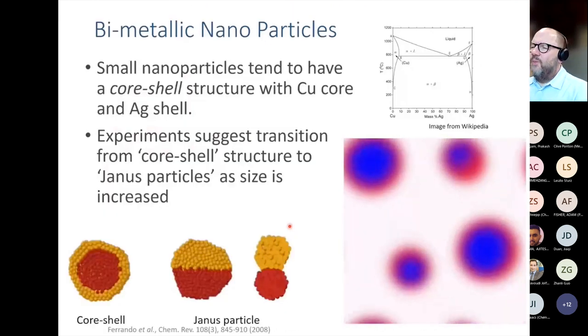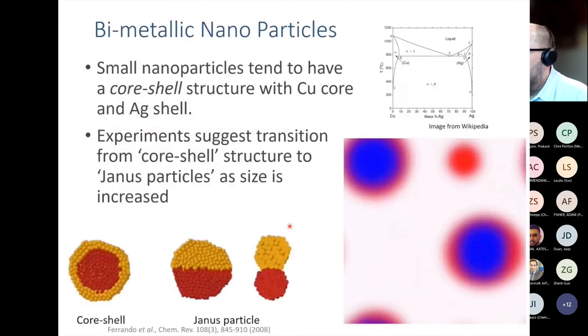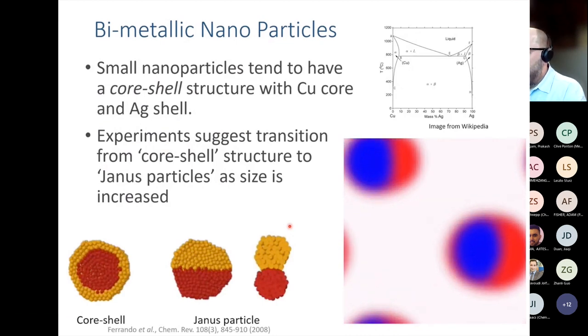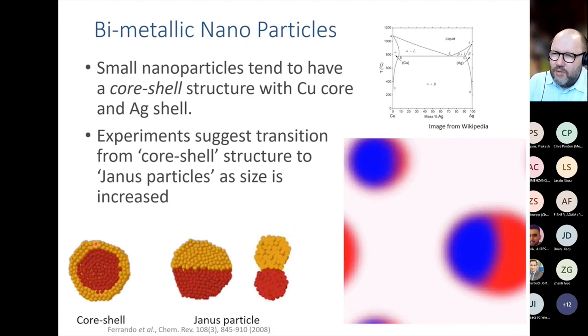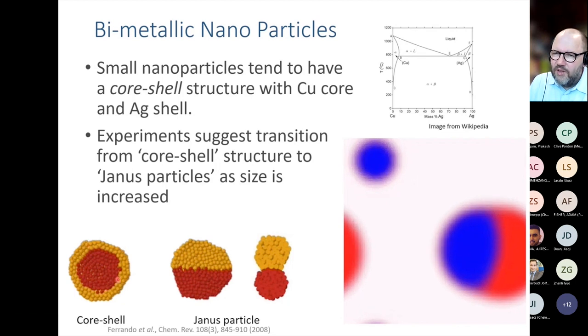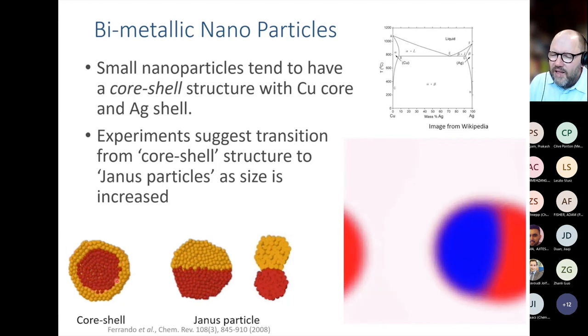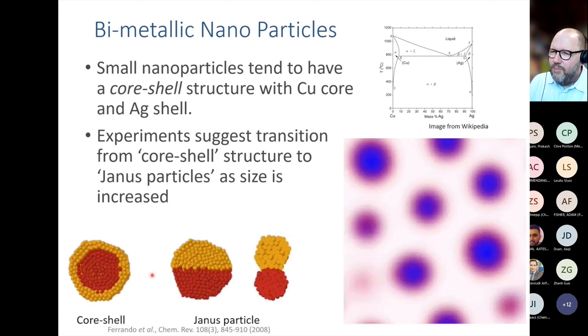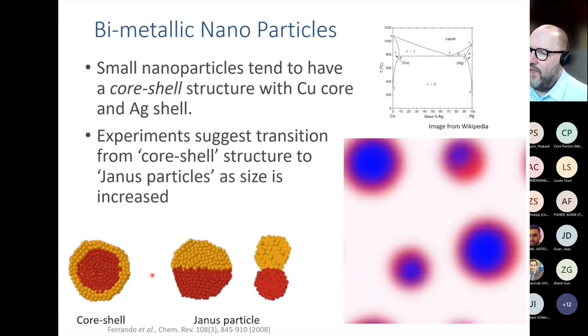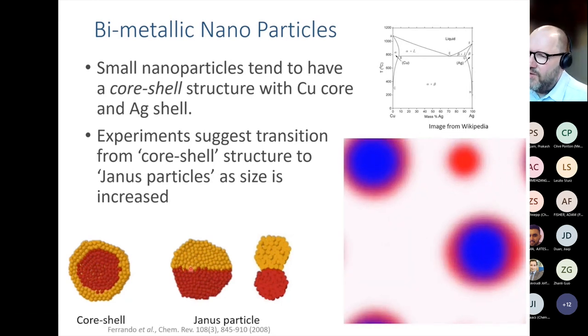This one I'd like to show where we use the same concepts in a very, very different context. This is for silver copper and phase separation appearing in that, trying to rationalize when we have nanoparticles in the silver copper system. When they're very small, they form what's called a core shell configuration with copper in the center and silver forming a layer on the surface. If they get bigger, they transform into a Janus type particle where one side is copper, the other is silver.